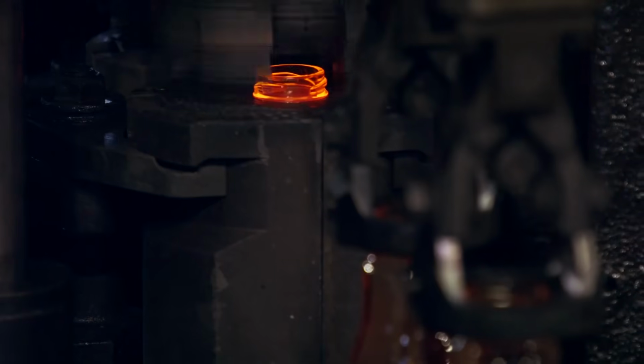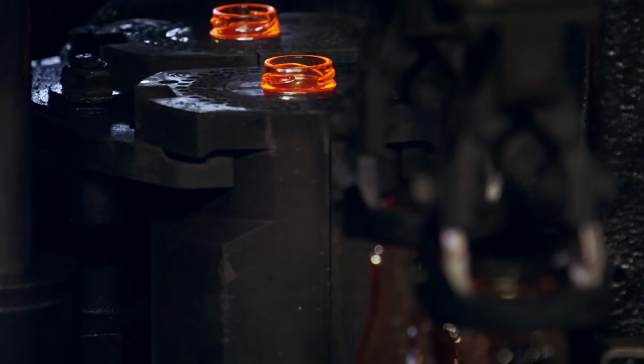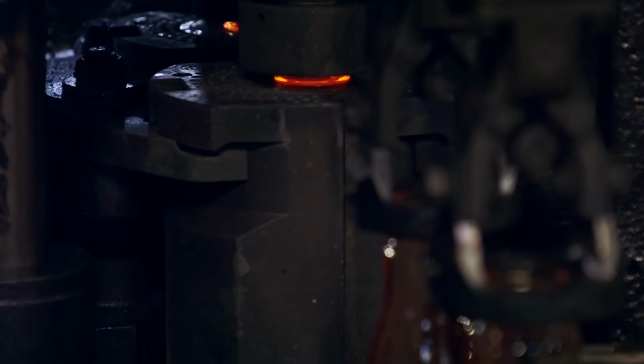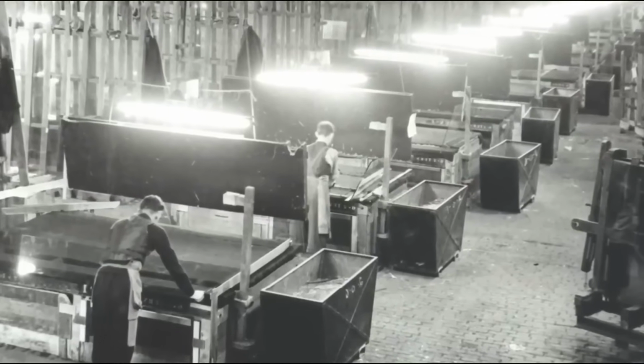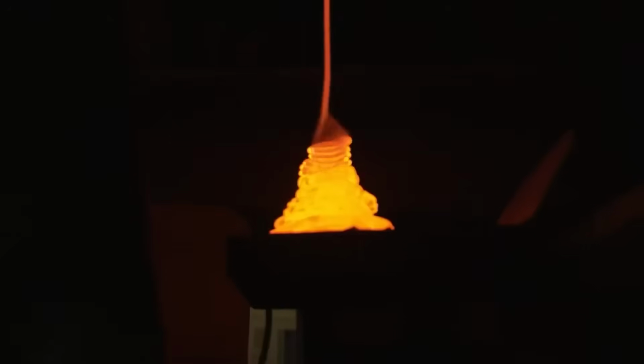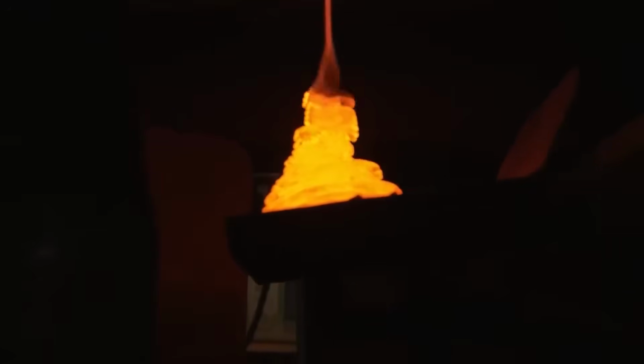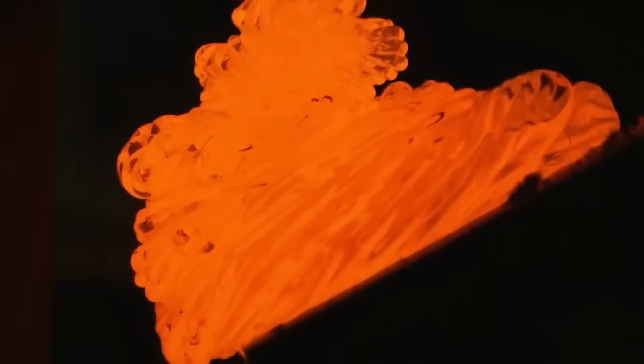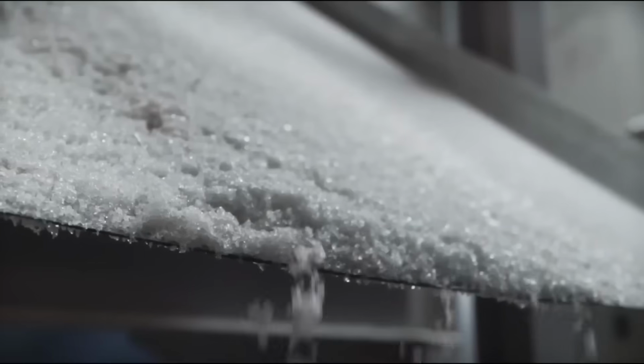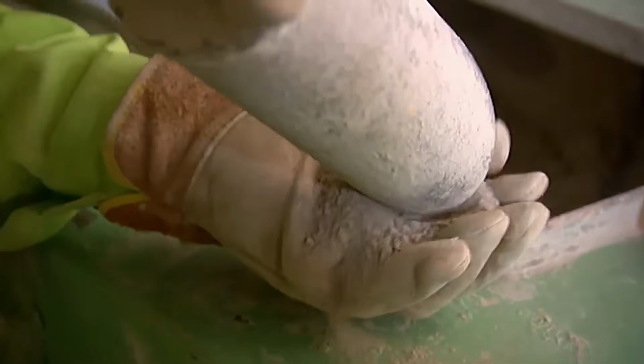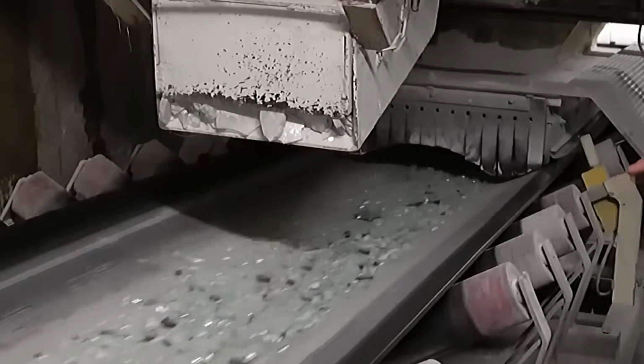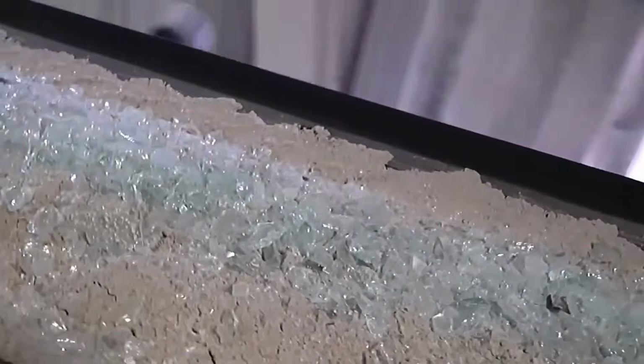Without it, the sodium in the glass would leach out slowly in contact with water, degrading the material over months. The ratio of these 3 components is tightly controlled. The standard soda-lime glass formula runs at roughly 73% silica, 14% sodium carbonate, and 9% calcium carbonate by weight, with the remaining 4% occupied by secondary oxides. A deviation of more than 1.5% in the sodium carbonate fraction shifts the viscosity curve of the melt. The glass flows differently at forming temperature, and the resulting sheet thickness becomes inconsistent.